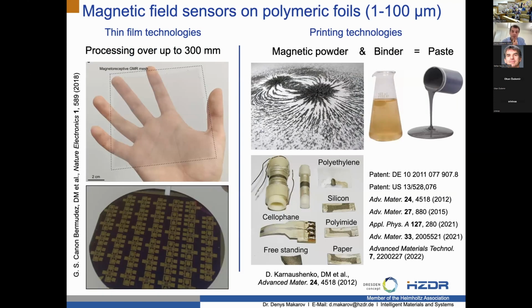Where I see a very huge potential of where this type of activities can impact the development of material science and also applications, it's a possibility to use such kind of flexible devices, but in the form of printed sensors. So instead of going from silicon wafers to polymers, you make another step. And now you say, look, I want to go away from thin films, and I want to fabricate some kind of feedstock material. Feedstock in this respect is a powder, let's say a magnetosensitive powder, which you have to mix somehow with a polymeric binder to create a paste. And this paste you can print using screen printing, dispenser printing, or simply painting on different types of substrates.